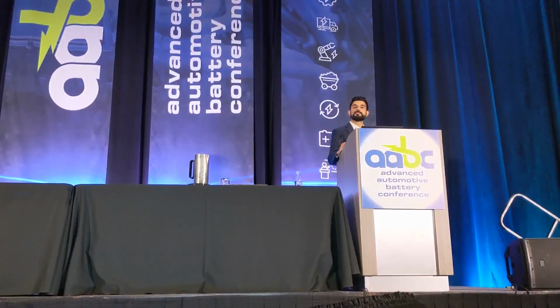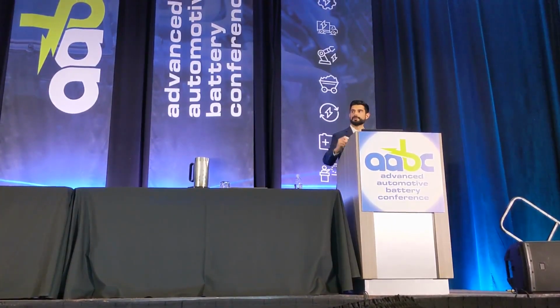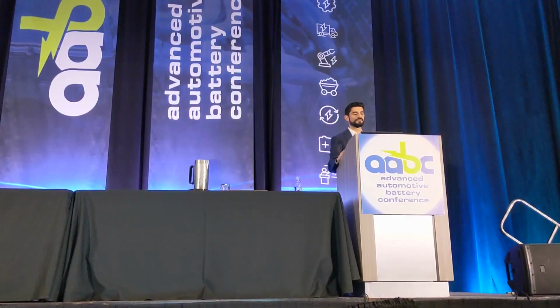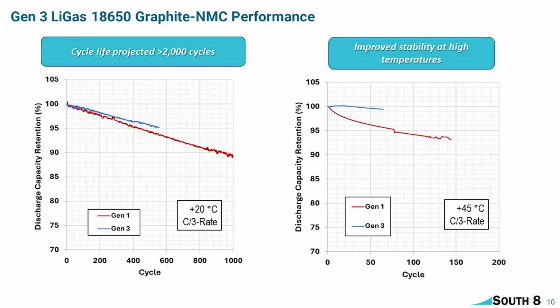The Gen 1 chemistry showed pretty good cycle life. Our Gen 3 chemistry is only improving upon that. So over here we show Gen 3 chemistry. It's a little past 500 cycles, but projected to be well over 2,000 cycles. This is a 2.8 amp hour graphite-NMC 18650.